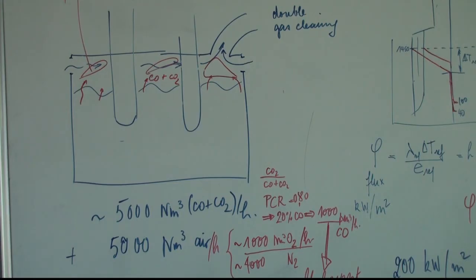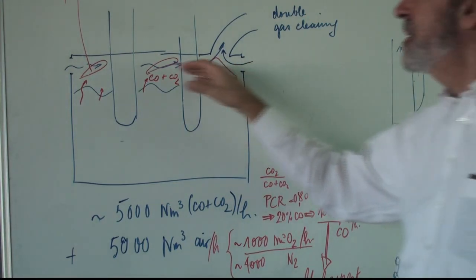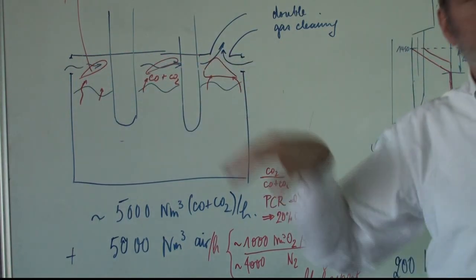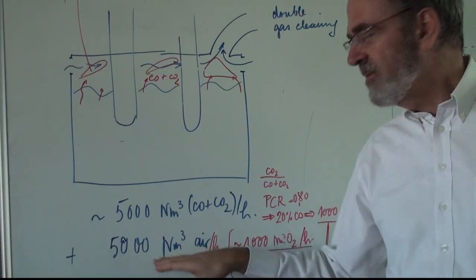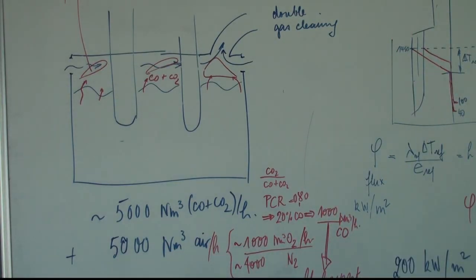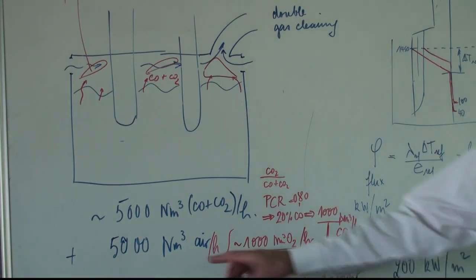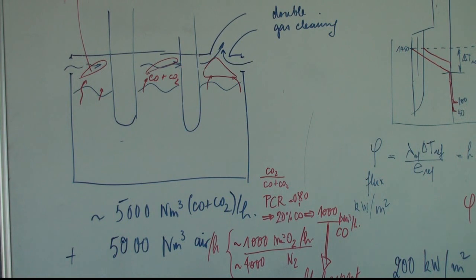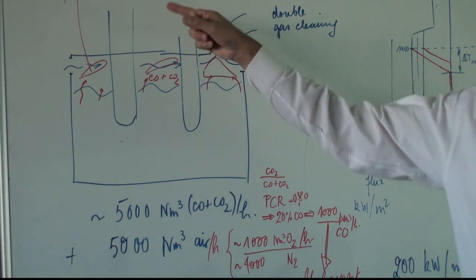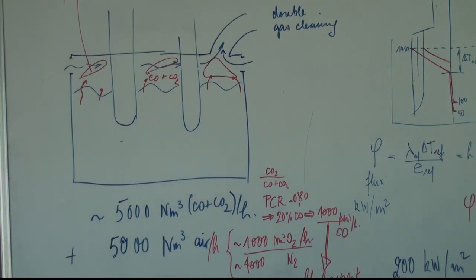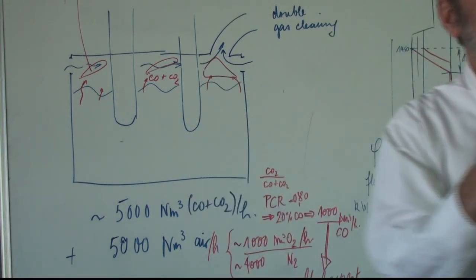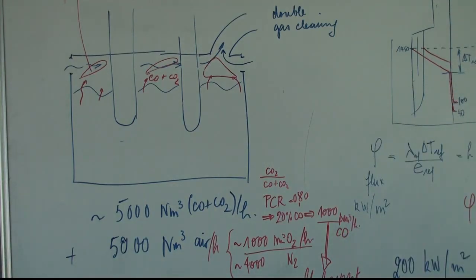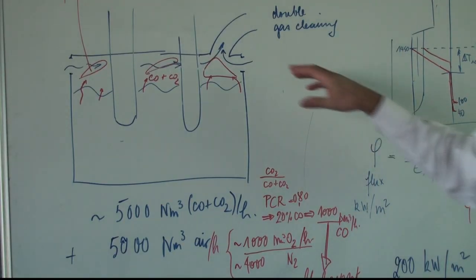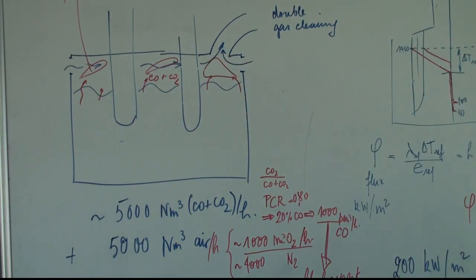And what I say is that if you have large openings at the top, you will suck in, I'm sure, more than 5,000 cubic meter air per hour. More than this. And only with 5,000, you already have 1,000 cubic meter oxygen. And this is already more than double of what you need to burn all the CO. So you can be sure that even if the flow is not very well organized, CO will find enough oxygen to be burned at the end. At least in this area, all will be burned.